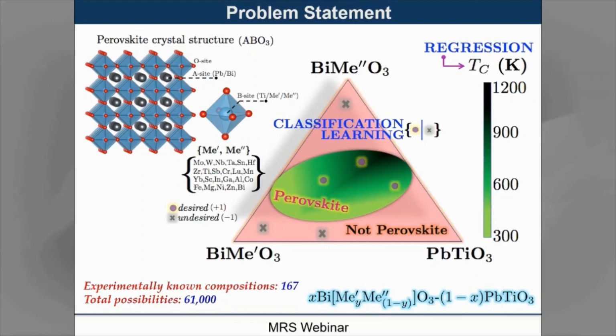So we were able to go back to the literature and build a training data set for this problem, where in addition to collecting data on the property of interest here, which is the Curie temperature, we should also capture data on whether this particular composition had in fact resulted in a perovskite crystal structure or not. So in fact, since this material has been under research for at least 4 to 5 decades, we were able to compile approximately 167 compositions from surveying the published literature.